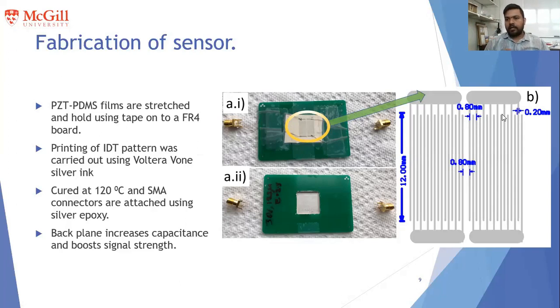It is an 800 micron wavelength design. That means 800 micron is the wavelength, the distance between two alternate fingers. The stretching is required to create tension in the film, which is essential for an acoustic sensor for better propagation of the acoustic wave. Also the two nodes of each transducer, signal and ground, are connected to an SMA connector for connecting to the VNA. We also printed the back plane, which improves the capacitance of the sensor and boosts the signal strength.